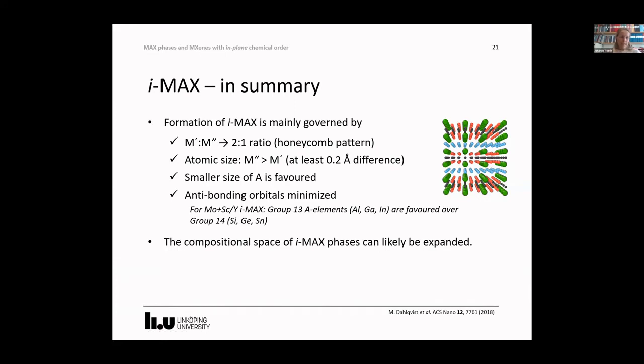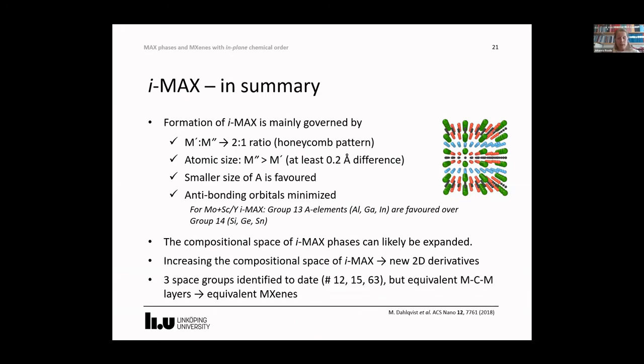Using these guidelines, we foresee a widening of the elemental space for the family of IMAX phases, and we expect more phases to be synthesized. Again, and most importantly, since IMAX phases are parent materials for 2D MXenes, we also expect that the range of MXene compositions will be correspondingly expanded.